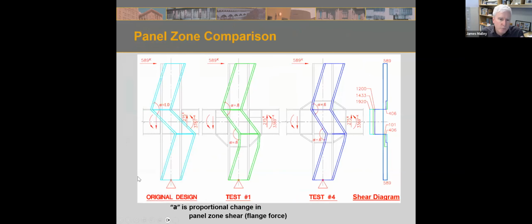This is another kind of way of looking at that on the original design. You can do, this was I think from the finite element analysis, you're getting a rotation of about 1 and still getting about 0.8 at the same force level with test 1 with the single haunch, but that drops down even to 0.6 in the double haunch. And you can see the reduction in shear demand that goes on as well in the panel zone. So it really helps to quiet down the panel zone and that kinking action.